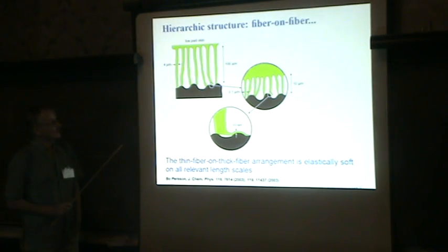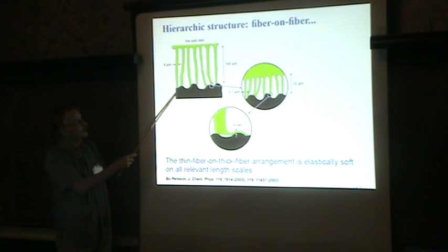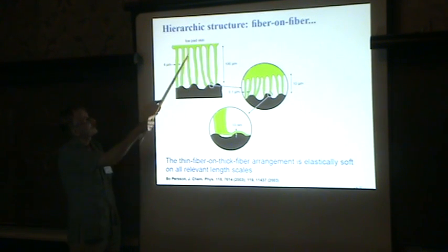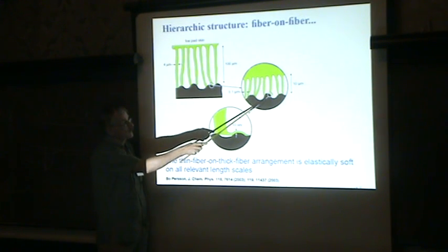And the most advanced organisms, the lizard, insects and the spiders, they have this hierarchical structure. And in my opinion, the reason for the hierarchical structure is that real surfaces have surface roughness on many different length scales. So if you have long wavelength roughness, to make contact here you need rather long asperities, and you can just bend them a little to make contact here. But if each such long fiber here would end with a smooth curved surface, you could still not bind here, because you have roughness at shorter length scale on top of this surface, which looks smooth here. So if you magnify here, you observe new surface roughness, as I told you before.